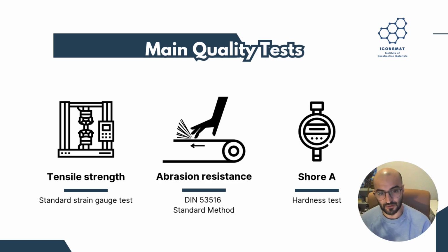And after a certain period of time, let's say 1 minute, 2 minutes, because of the friction and those abrasive interactions between the drum and the polyurethane, a few grams or a few tens of grams of the polyurethane will be scratched off, and then the remaining mass of the sample will be measured. If it's less than a certain threshold, it would tick off and become an abrasion resistant type of splice, and that's what we need. There is also another test, the Shore A hardness test.